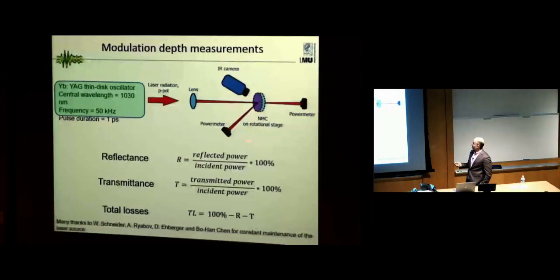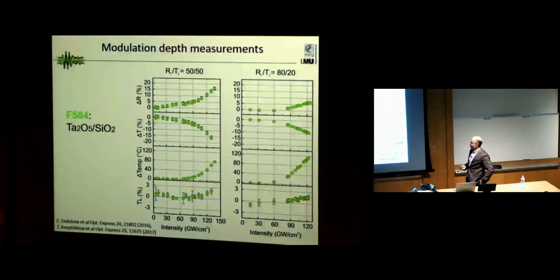And basically we made a very simple experiment. We have our laser light and we focus it on our sample. With a power meter, we measure the reflected beam and the transmitted beam, and we also measure the temperature with an infrared camera. And actually, what we observe when we adjust this filter by tuning the angle is 50 to 50%. That is, 50% of the light is transmitted and 50% of the light is reflected.